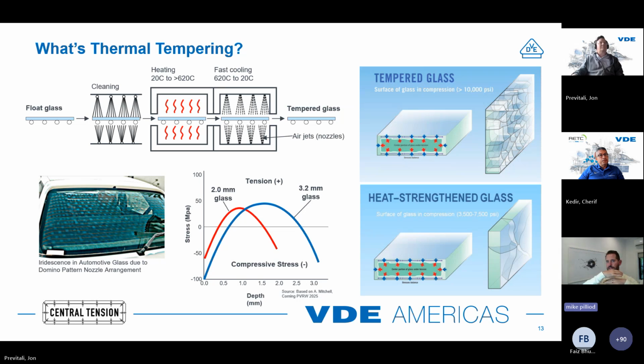In flat glass, you would tend to have either ribbons or straight lines that would end up having sort of anisotropy, where you basically have stress patterns that look like lines in your architectural solar glass. As you look at the stress versus depth graph, you have two curves here. One's a red curve of 2 millimeters, and one's a blue curve of 3.2 millimeters.